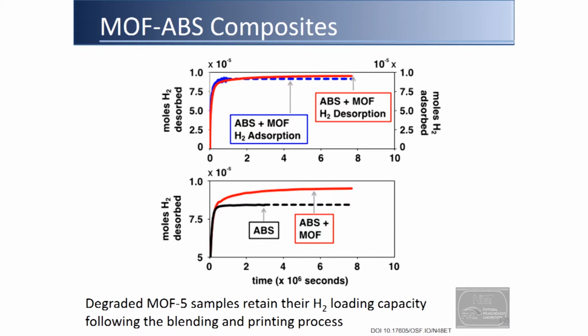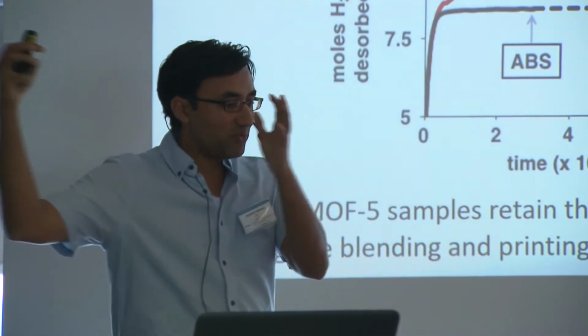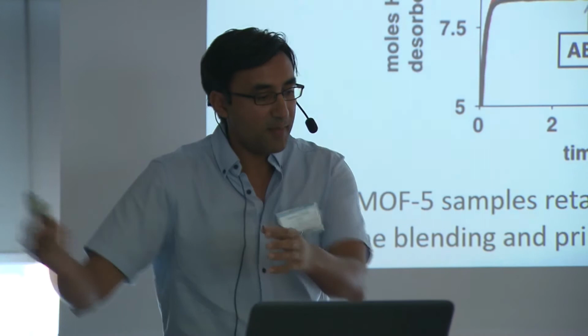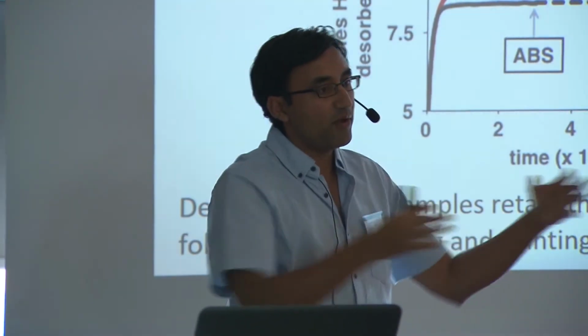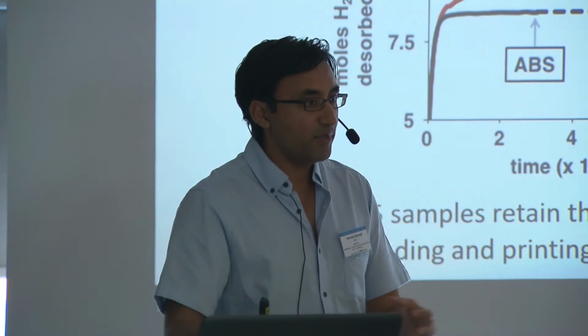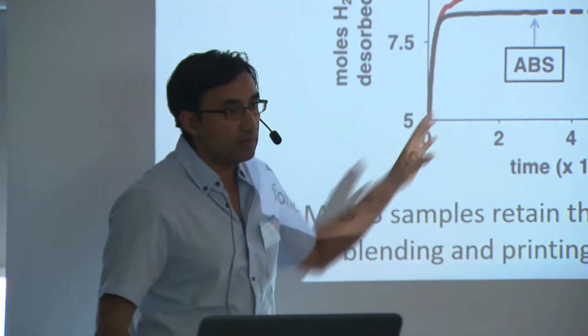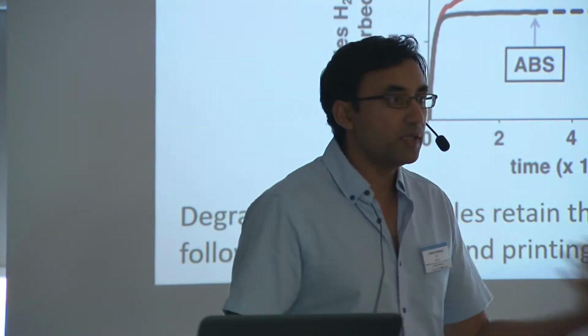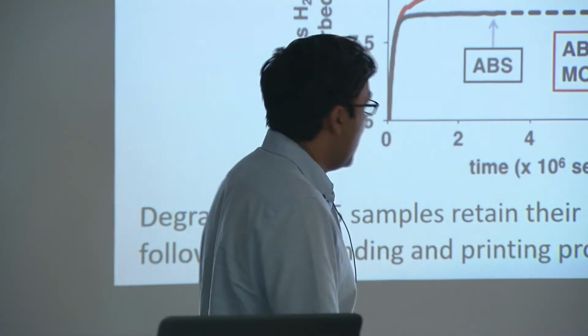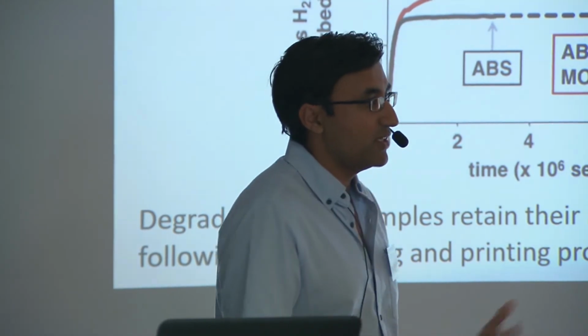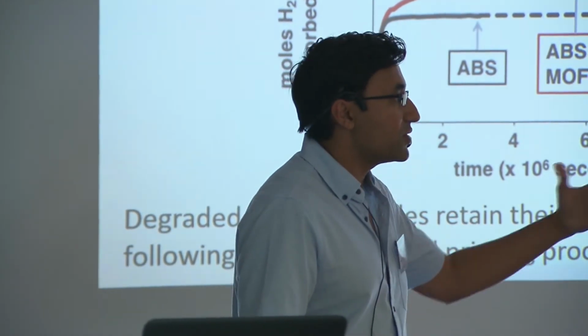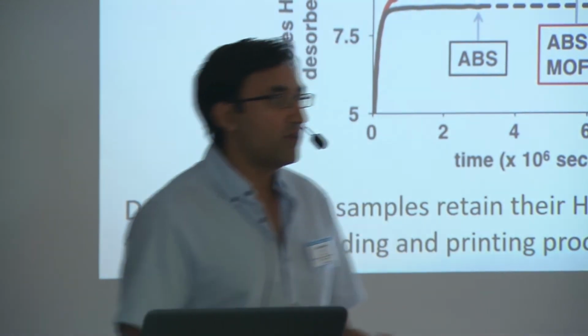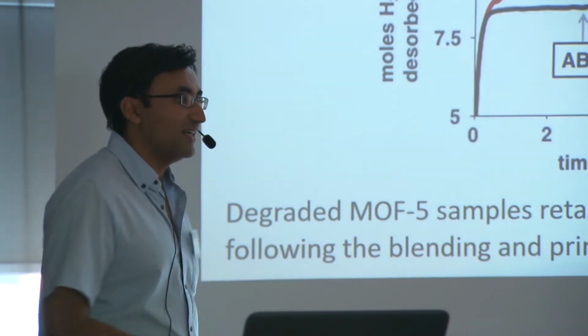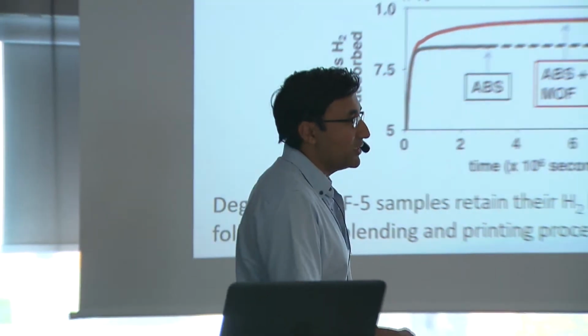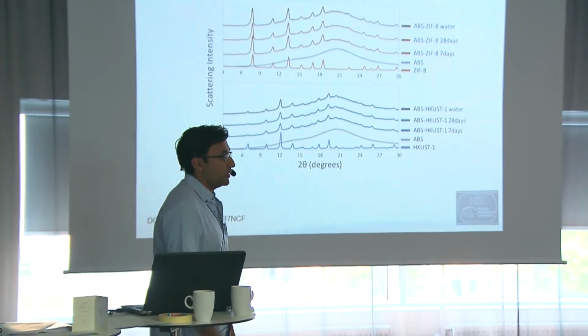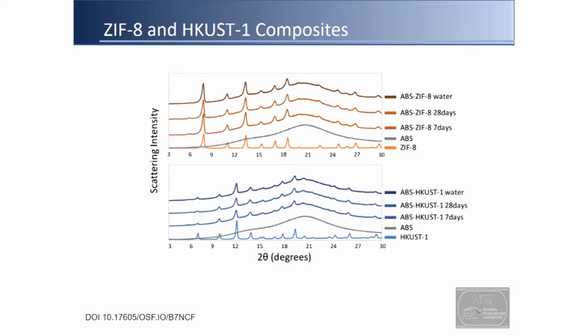And the reason, unfortunately for us, it turns out, was because somewhere between the synthesis and purification and the blending process, our MOF samples were exposed to humidity and they decomposed. So the values match up with what people have seen in literature for decomposed or degraded MOF5. So while this was a positive in the sense of, yes, the idea works, you can process all these materials and change the basic properties of MOF, it was a little disappointing that it didn't quite work the way we wanted. So that's why we switched over to HKUST-1 and to ZIF8, because they are more robust against humidity.